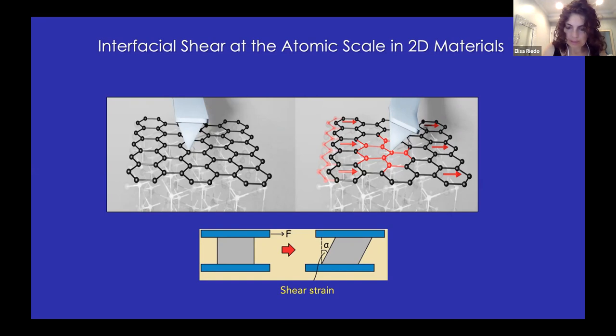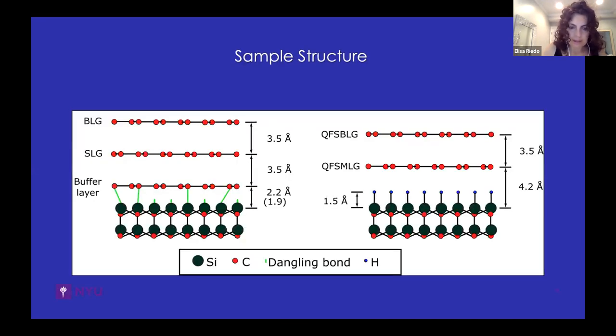We started to play with this type of experiment with two different systems. One is a regular epitaxial graphene system where, like I described before, you have freestanding graphene and then you have this famous buffer layer, which is a mix of sp2 sp3 bonding with the silicon carbide substrate. So it's really an interfacial carbon layer. And then we have this system where hydrogen has been intercalated between the buffer layer and the silicon carbide, and so this buffer layer is released and becomes a quasi-freestanding monolayer graphene, as you can see from the name here.